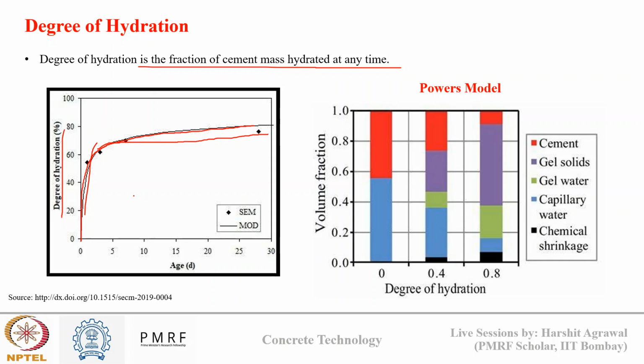Okay, so at 28 days we generally say that more than 99% of the hydration that should have happened will happen. However, this statement is not true when we add mineral admixture to the system. Why? We'll see later on when this topic comes up around week 3 or week 4 content, that mineral admixtures start to hydrate when CH is produced by OPC. So the CH that is produced by OPC is consumed by mineral admixture to form CSH. Okay, so this CH production takes time, and then consumption will be done by mineral admixture, and then CSH will form. So instead of reaching the 90 to 100% hydration limit at 28 days, for mineral admixture, hydration can grow up till 120 days also.